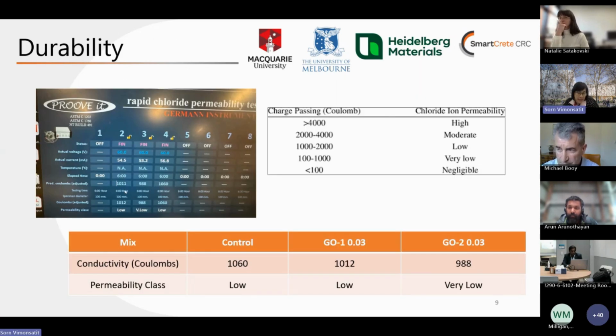Besides the mechanical properties, we've also done some durability tests, mainly at the University of Melbourne. The first one is the rapid chloride permeability test, according to ASTM C1202. It basically checks the coulomb charge passing, according to this table. The control already has a very low permeability passing. For the concrete mixed with graphene, we also find it's very similar on the lower side. So these results are very promising, that having graphene in the concrete can improve, even if only slightly, the chloride permeability properties.